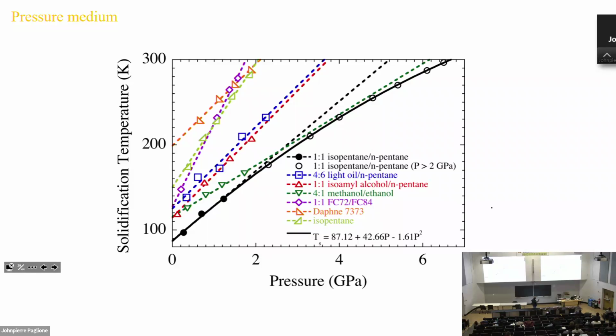So if you just look at this graph, it seems like this one, the 1-to-1 ratio isopentane and n-pentane, seems to be the best. It seems to have a wider range of pressure where it solidifies. In reality, for example, for the piston cylinder cell, we actually prefer this Daphne 7373. This is a mineral oil, some organic oil from Japan, and it has a smaller pressure range. But for a piston cylinder cell, this is enough. And it turns out, with this one the pressure doesn't change much as you cool down the temperature, which is also important. This graph doesn't tell you the change of the pressure. It only tells you in what pressure range it solidifies. But for example, if you do a Bridgman cell, you probably want to use one of these.